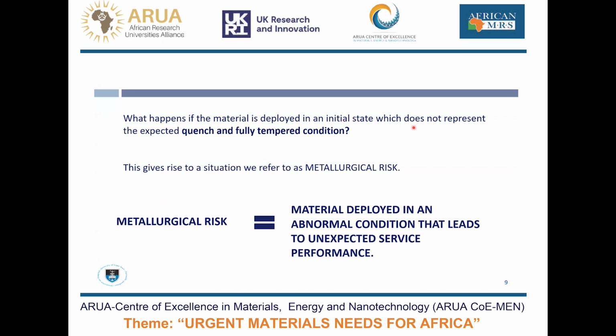What happens if the material is deployed in an initial state, which does not perhaps represent the expected quench and appropriately tempered condition? In other words, a property that we can then predict its life. If that doesn't happen, and we don't know that that hasn't happened, it of course gives rise to what we know as metallurgical risk. So I always teach my students that mild steel is so popular in engineering because in fact there's very little metallurgical risk associated with it. You can do anything to mild steel and it almost always behaves the same way. It's so easily weldable, very little change in the properties across the weld, and consequently what you see is what you get. But that's not the case with very complex materials used at high temperature and high stress.